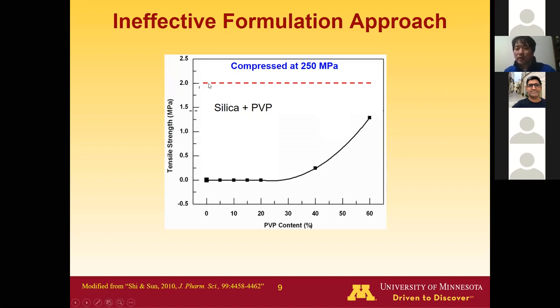We apply this 2 MPa as the strength we want to achieve when you make tablets. It doesn't mean you have to reach this strength to make a tablet with acceptable strength, but if you do have this strength, you most likely don't have any worry about sufficient strength. So we use 2 MPa as a sort of conservative criterion for the strength of tablets. You can see even up to 60% excipient in the PVP, the strength is still not as strong as what we desire. So this says that just simple mixing, the formulation approach,